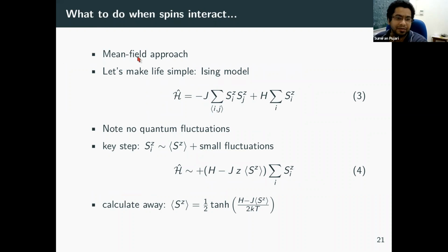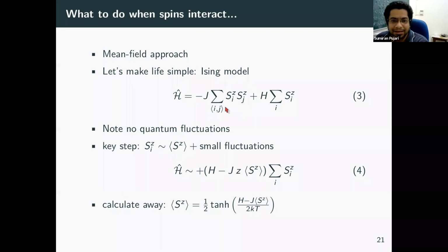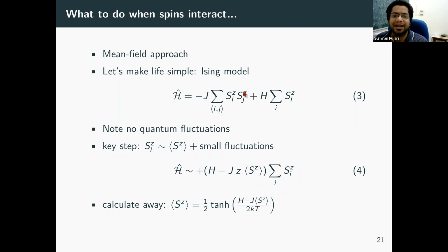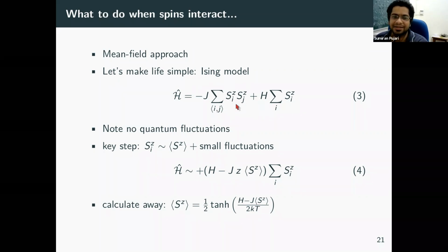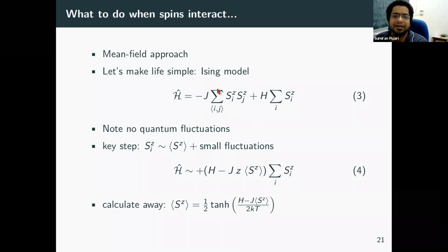And here, at least in terms of understanding experiments, often mean field approaches prove quite effective. So one simple example where we can see how mean field approaches work is the Ising model. In the Ising model, spins again interact, but they interact in a special way. Only the S_z component of a spin half interacts with the S_z component of a neighboring spin half. So this is some condensed matter notation that you sum over all possible bonds on your lattice. This minus J implies that the spins want to line up, and you can put an external field also in the process.